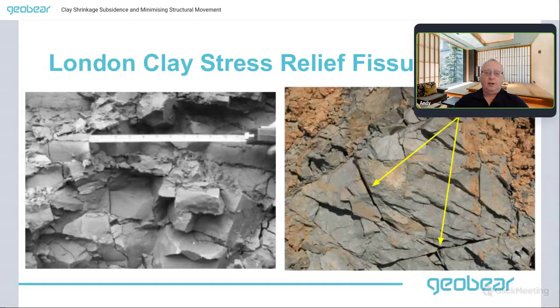So this is a close-up look at the London clay in an excavation. What you notice when you look at the actual formation in a cutting or an excavation is that the clay itself doesn't really look like a clay. It looks quite blocky. It looks quite fractured, and you can see lines of discontinuity within the actual clay. And these are natural features, often called joints, and they're formed due to the diagenesis of the clay as it was laid down and compacted over millennia, and as it was raised near surface due to tectonic activity. These fissures open up under stress release, and so they are natural and common phenomena in these types of over-consolidated clays, which are called fissured clays.